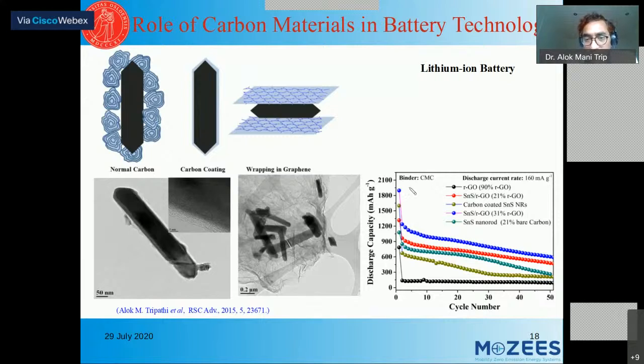You see in the first cycle, we are getting around 1800 milliamp hours per gram. In the initial cycle, we have losses. As I explained in my previous lecture, we have lots of side reactions in the initial cycle. So when you get the product in the market, it is already activated. Generally at the research level, we don't talk about activation, but in an industrial product, we have an activated cell. When you purchase the cell and measure it with a multimeter, you will find around 2.5 or 2 volts for lithium, although its potential is around 3.7. So it's already pre-activated, meaning these losses are already managed inside the cell.